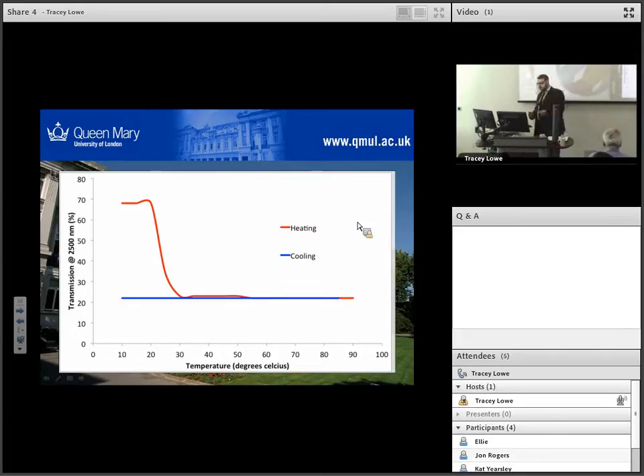Some of the crystallite sizes in the films we've been producing are 3 or 4 nanometers at least, from the Scherrer equation, which again you can probably trust about as far as I can throw this bench. But certainly there's some very, very small crystallites, and they're being oxidized.